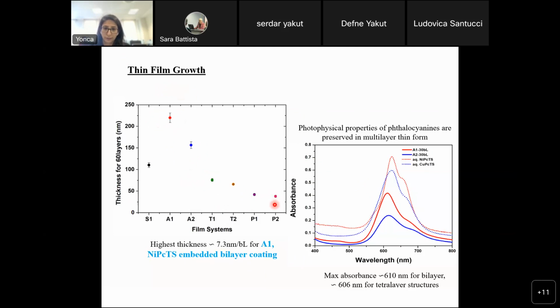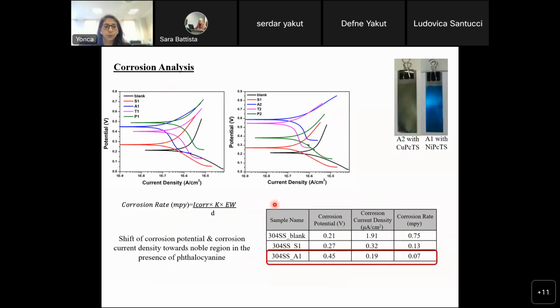So what about the corrosion then? Do they really help? So to do that, I've checked the Tafel measurements, and here you can see the current density versus the potential for the nickel and the copper case. So let me explain what it means. First of all, this is how it looks for the copper metalated film on a stainless steel surface, and this is how it looks for the nickel metalated film on the same metal surface.